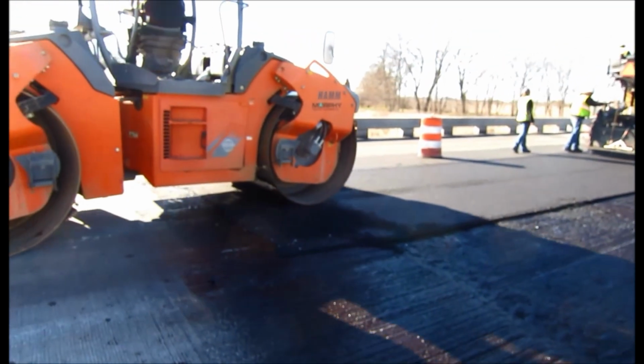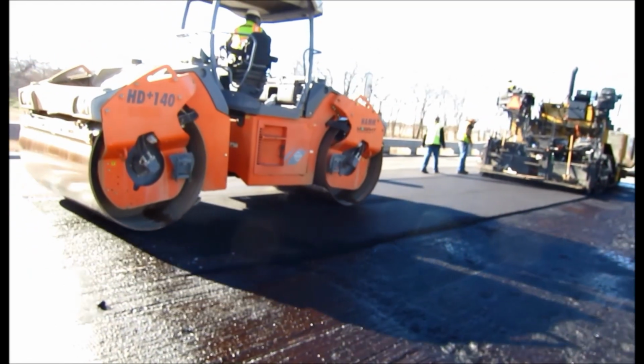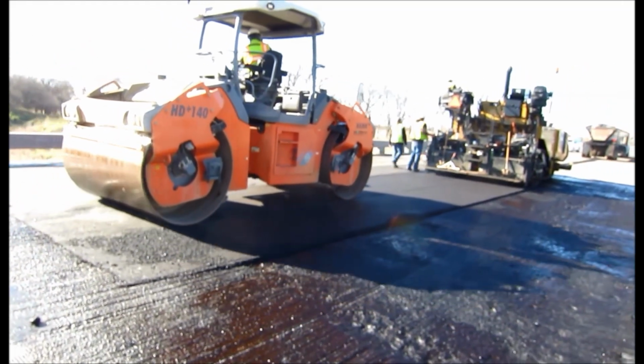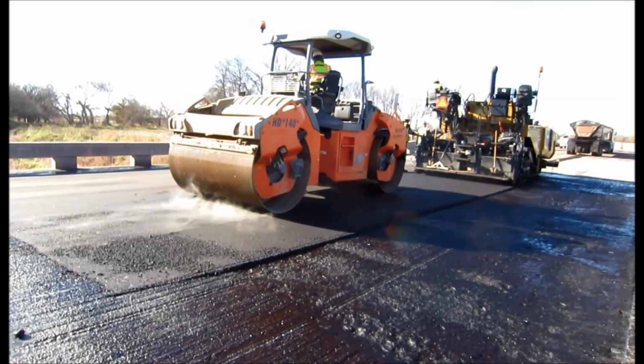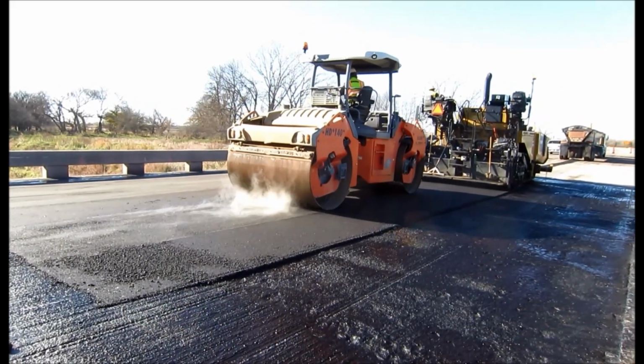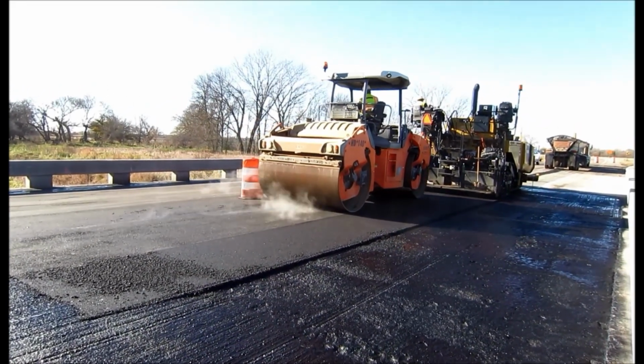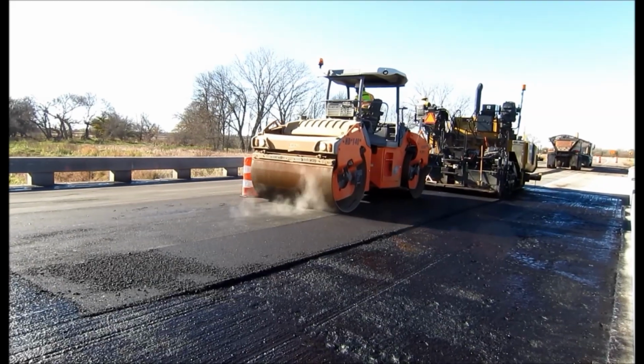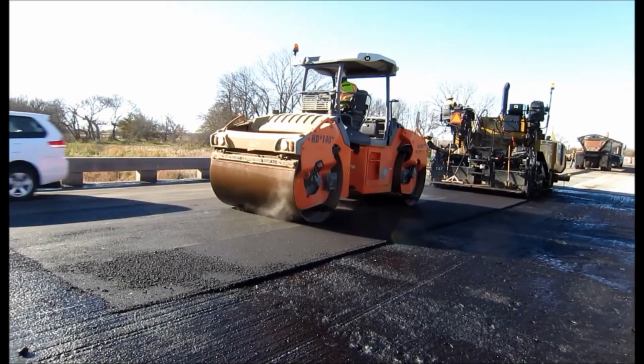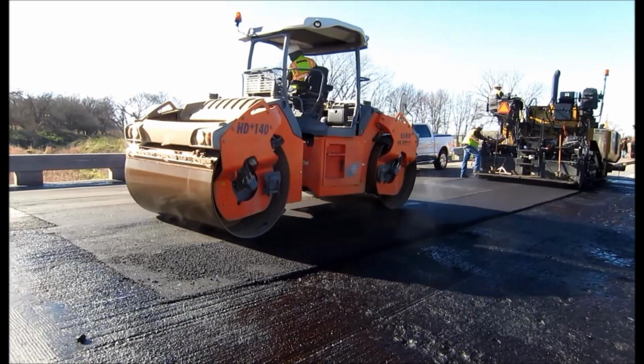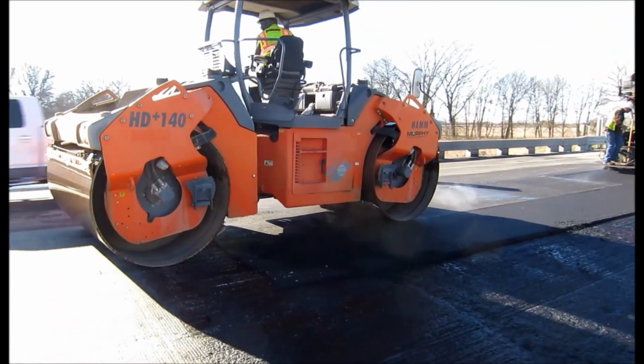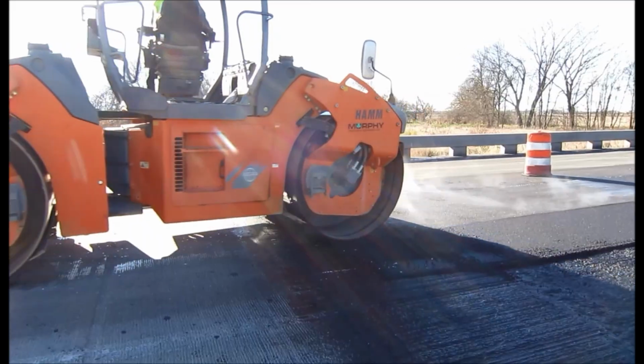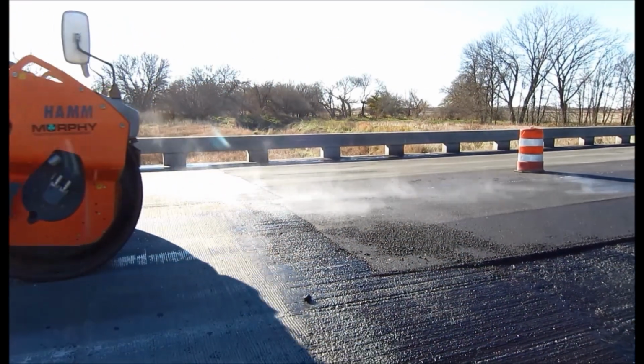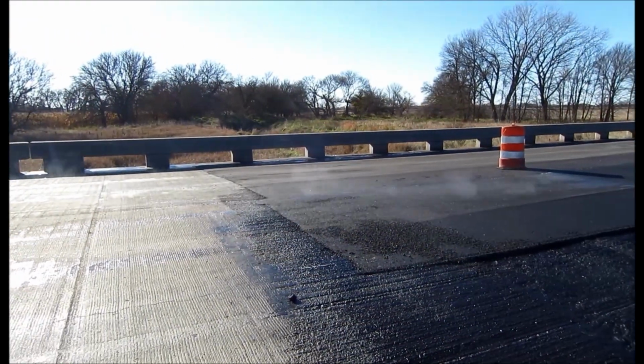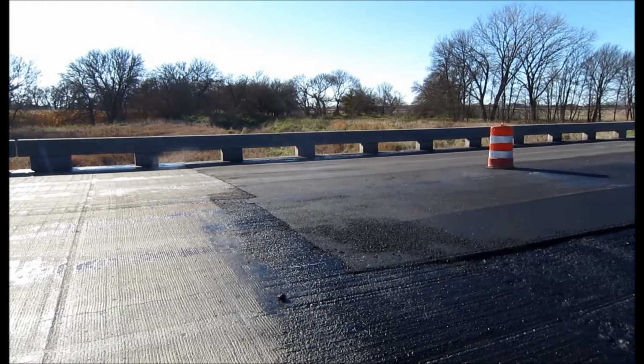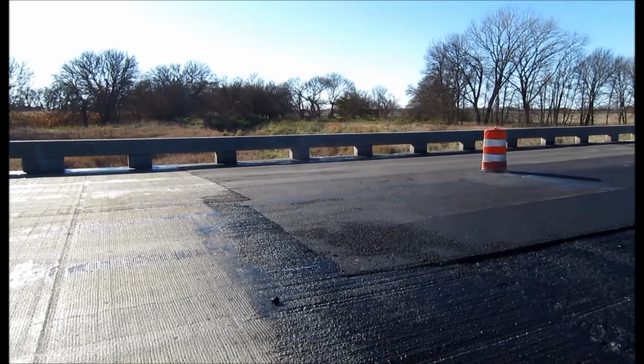In this video, we are looking at a roller about to start its first pass on a cold morning. The asphalt is being placed on a milled concrete surface on a bridge approach section, moving away from the bridge. The paver's screed was set to 0 and gradually opened up to the design height as it moved away from the starting point. The roller must start making its first pass quickly due to the thin asphalt layer and cold temperature, causing the asphalt to cool. The roller backs all the way off the asphalt to adjust its direction before returning to the mat to prevent tearing.